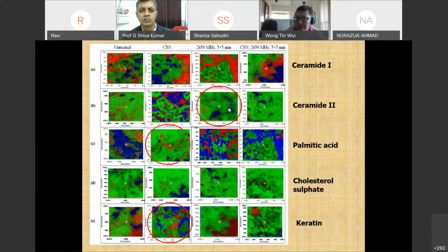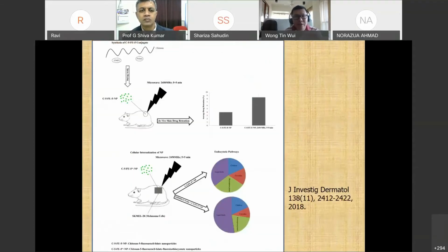So you can see both chitosan nanoparticles and microwave fluidize different lipid compositions. So the combination of both will synergize their skin drug delivery capacity. Now, in the same study, we further modified the chitosan nanoparticles. We designed chitosan 5-fluorouracil nanoparticles with folate conjugated to them. Folate is a targeting ligand for the folate receptor that is available on the surface of the melanoma membrane. So using chitosan 5-fluorouracil folate conjugate nanoparticles, the same outcome has been derived.